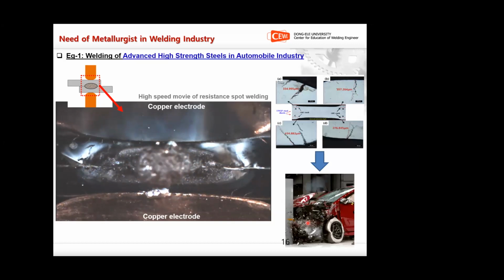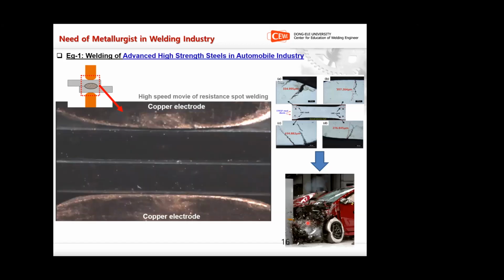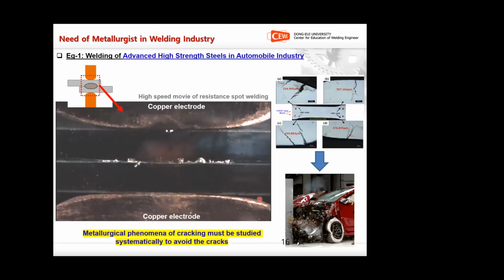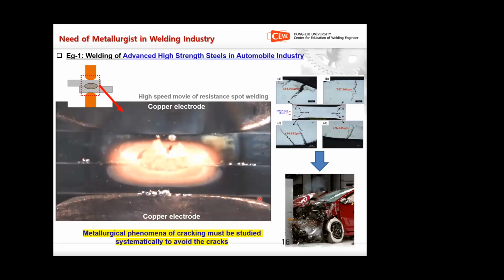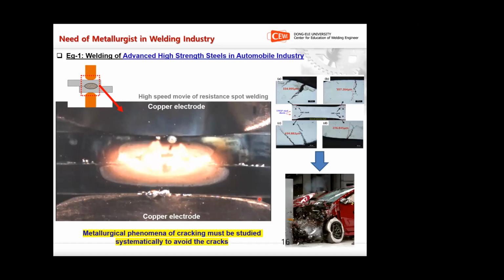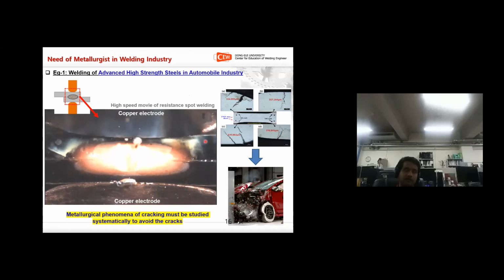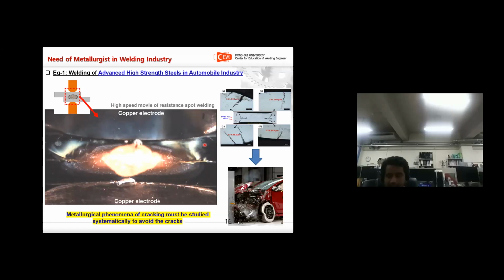But how to eliminate them? If you want to solve a problem, you first need to identify the reason behind it. So we need to conduct a detailed metallurgical analysis to reveal all the metallurgical phenomena of cracking. If you know the mechanism of cracking, then we can avoid it. When we looked at this, we found that these are caused by liquid metal embrittlement cracking, which is due to the liquid zinc. The liquid zinc penetrates the steel sheet and makes the cracks. So we need engineers or researchers with a strong background in metallurgy in order to solve these problems. That is the case of the automobile industry.